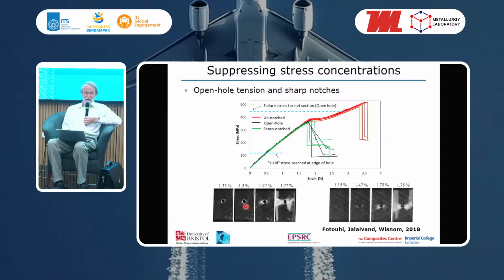So you can see this on these images here. Even down here, we've got some fragmentation. It's perhaps not very obvious on this plot, but near the hole there's some fragmentation that has started, then it grows across the width as you get nearer the failure, and when you get to this point here, it's fragmented across the whole of the specimen, and at that point it does fail. And we get a similar response whether there's a hole or a sharper notch there. So it has successfully reduced the notch sensitivity.